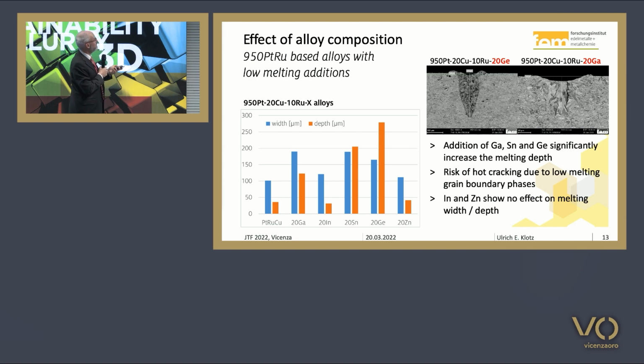We get this keyhole mode if we add germanium. In the case of gallium, we also get the keyhole mode, and we get a lot of cracks. So there are some critical alloying elements.